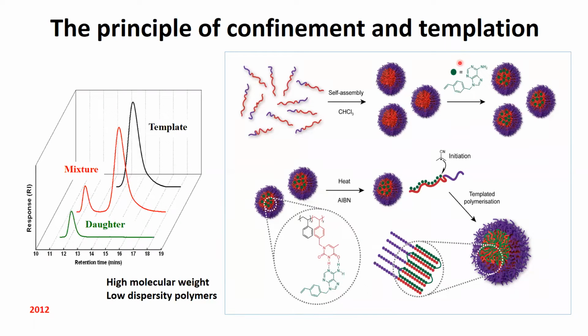We also decided to use the same nucleobases that DNA uses for templation to allow us to template the monomers we wanted to polymerize within our polymer particles, using confinement and templation to make polymers. We were able to make these daughter polymers that were really high molecular weight, low dispersity. This approach is absolutely bio-inspired. It makes us think much more about the methods: if we can improve the methods and complexity of the methods we use to make polymers, we can make more complex polymers.